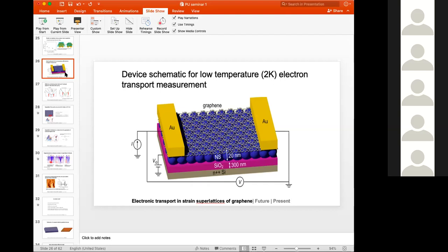Obviously, one of the first things to look at is the Raman. There are also some things you can look at optically. If your graphene sheet has folded over, there are bilayers, trilayers of graphene, or rips in the graphene, you can observe that just by looking under a microscope from the color contrast. Then we also do atomic force microscopy to locate which look like the good regions of graphene on silicon dioxide. Then we look at the Raman spectra.